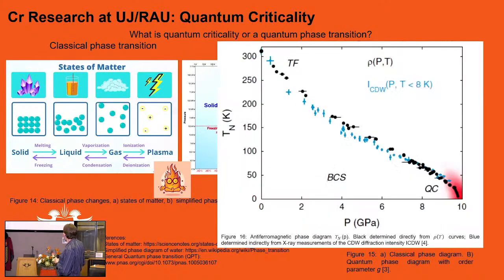Now some of the first studies on chrome, on quantum criticality, were actually done on pure chrome. Here the authors effectively tracked the Néel transition by applying pressure, very sensitive, because you can adjust, measure, adjust, measure. They don't, of course, tell you that those are many different samples over a lot of time if you actually dig down into their own data. Because even here it becomes very difficult.